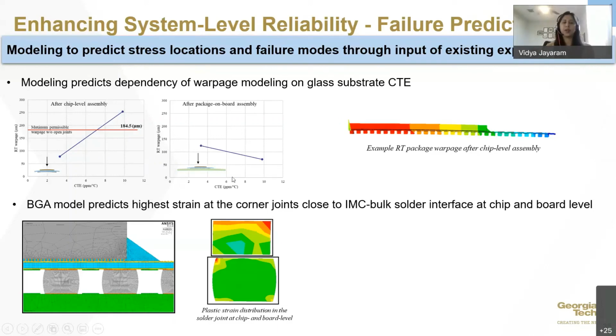But we saw a trend where with increasing the CTE, the warpage was reduced. And then for a BGA model or a thermomechanical stress prediction, we had a 2.5D model design, and we subjected it to thermal cycling stress to see where on the joints or where in the package would be the high stress locations.